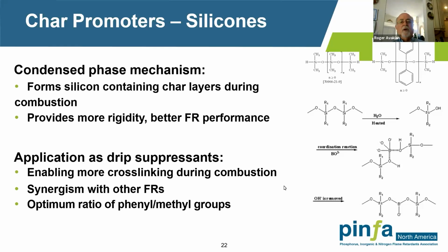It typically enables more cross-linking during combustion. And like I said, it is synergistic with other flame retardants. Again, not all silicones work the same. And we'll talk a little bit later about some of the issues here, like making sure that the silicone material is compatible with your polymer. As you know, the silicones are typically very non-polar, and so you can have some compatibility issues during compounding and potentially even at rest. You want to make sure that the silicone doesn't migrate out to the surface. So again, some things to keep in mind here.